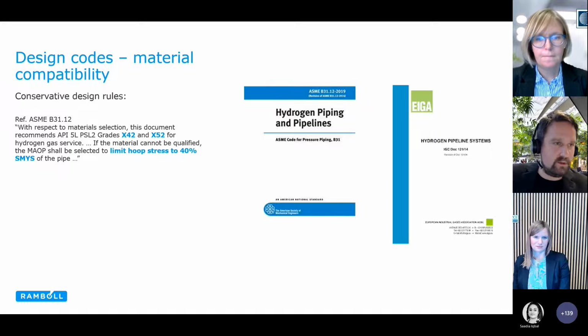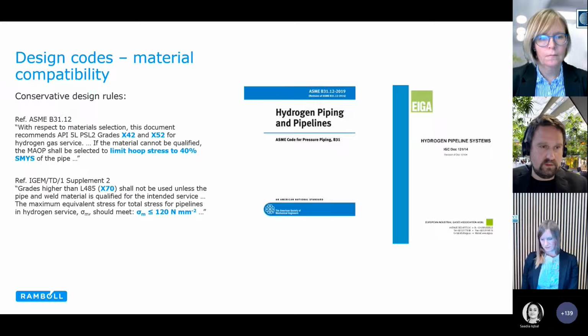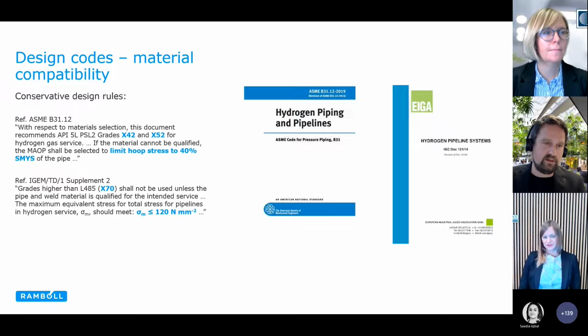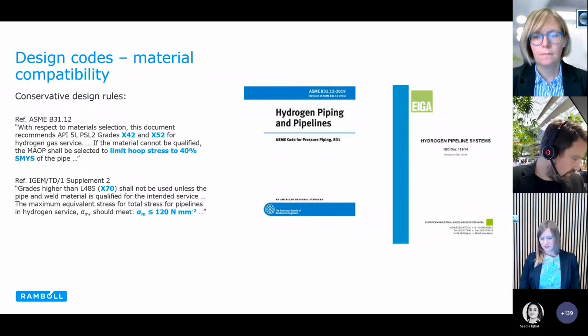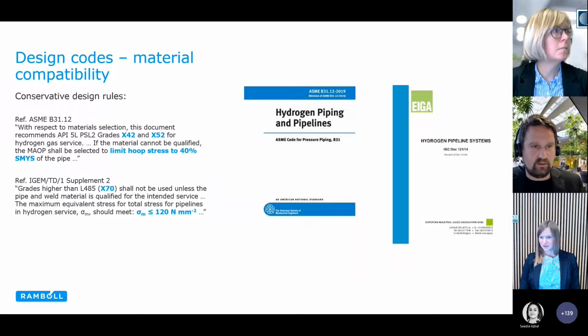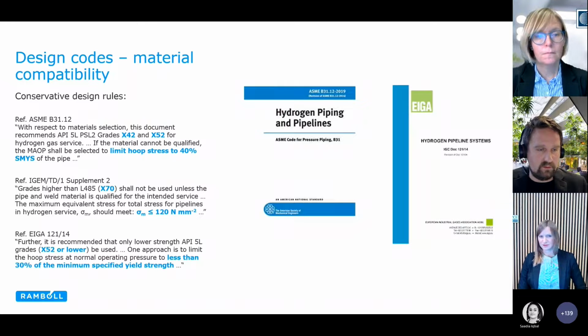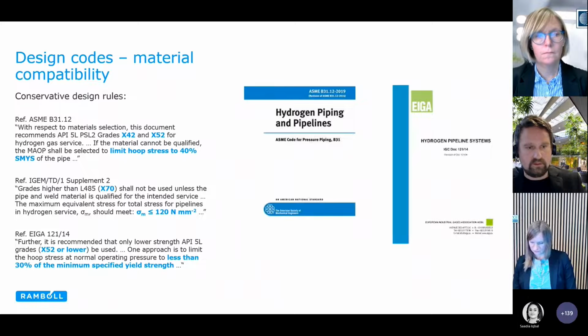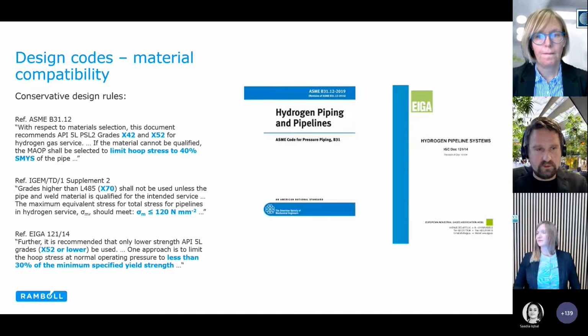Just focusing on the highlighted words, the ASME is saying that you should use X42 or X52 unless you do more qualification, and if you do not meet this qualification, you limit your hoop stress to 40% of the yield strength. There's a similar phrase in the IGEM. It's even more stringent, limiting the allowable stress in the pipeline to 120 megapascal, which translates into a utilization of somewhere between 0.25 and 0.3, depending on the yield strength of the pipeline. And then the EIGA has an X52 or lower recommendation and a limit of 30% of the yield strength. So every code has some restrictions, but they are not identical across all of them.